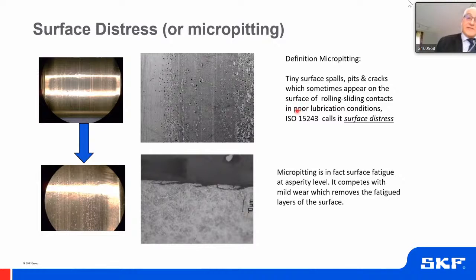There is obviously a very good, very well-known definition of this failure mode for rolling bearings in this ISO standard. There are also ISO standards for gears describing micropitting. It looks like this when you have a surface. You see these shiny bands here. If you look closer, you see some pits. If you go into the microscope, then you see some clear microspalls. And when you make a cut in the transverse direction, you see that these are really shallow cracks. And this is typically what we call surface distress.